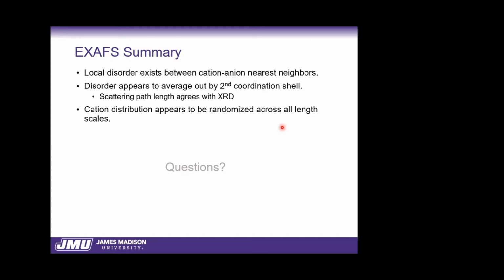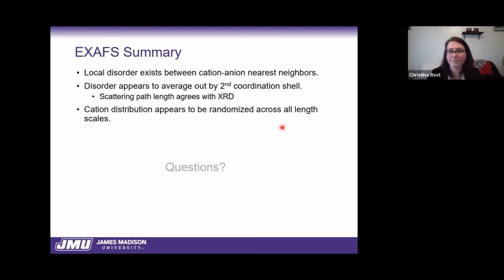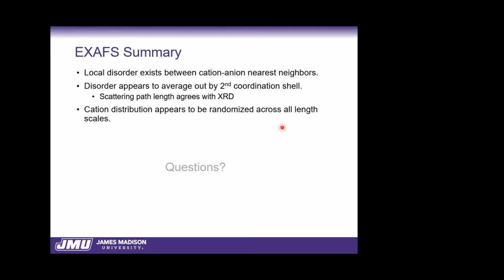And then my second question was, I missed the bit where you were talking about the impact on the first shell coordination, but I think I understood that it remains octahedral, but is that right? Yes. But then I guess if the oxygen sublattice is disordered, that probably destroys the center of symmetry, and so then you switch on pre-edge transitions in the K-edge XANES.